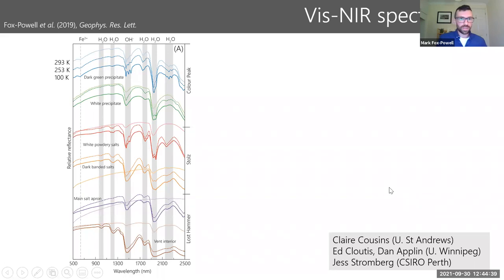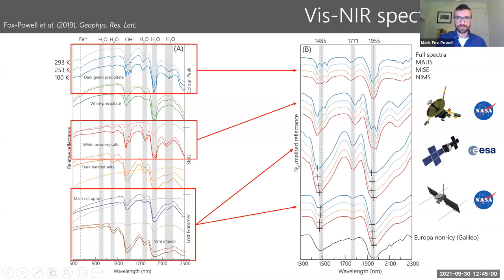So what we did is we exposed samples of these salt deposits to Europa surface conditions of temperature and measured near-infrared spectra, near-infrared reflectance spectra. And that's what you're seeing here, is the three springs we visited. I haven't mentioned Color Peak simply because it's dominated by gypsum and calcite and is less relevant to Europa.